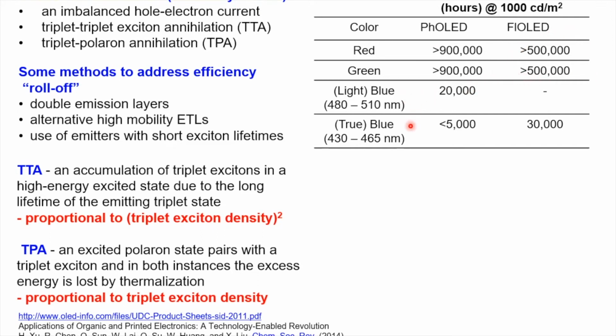However, for the blue, as well as light blue and true blue OLEDs, for the phosphorescence, they only have stabilities of 20,000 hours. And for true blue, that drops down to 5,000 hours, so extremely poor performance. And it's actually worse than that of the fluorescent OLEDs as well. So oftentimes in some of the commercial devices, they will use a lower efficiency fluorescent emitter for the blue component rather than the higher efficiency, but less stable phosphorescent emitter.